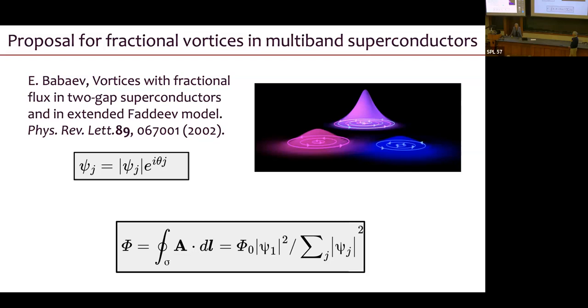So I'm not aware of people seeing that kind of non-azimuthal symmetry in looking at vortices magnetically. And I think it makes sense that it's much harder to see that magnetically because the magnetic field coming from the currents is very long range. So if you have a subtle variation in how much current is flowing, it would lead to a much more subtle variation in how much magnetic field you have at different regions. It's just the nature of the current flowing and averaging over all the currents that it tends to smooth itself out into a cylinder pretty quickly. So I'm not aware of that having been seen with magnetic imaging, but from scanning tunneling microscopy, definitely.